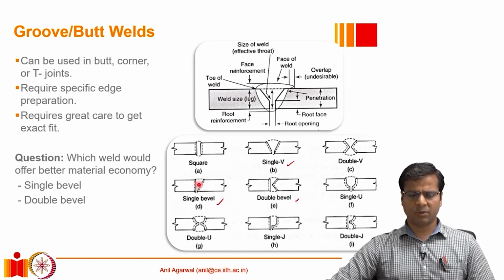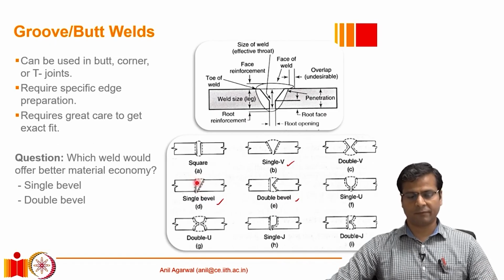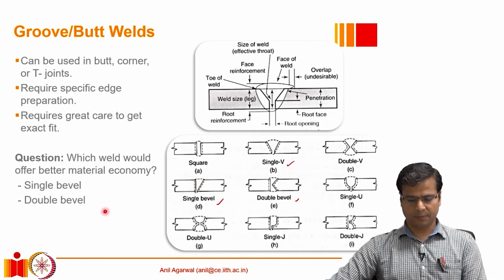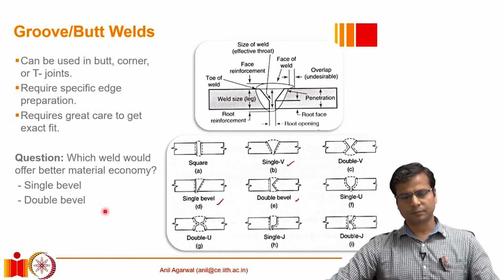So if that angle has to be maintained, and the depth is 18 millimeter, here we can calculate how much material has to be first removed in form of a groove and then filled back again with the filler material, right? And then we can calculate the area in a double bevel also for the same angle that has to be maintained. And you can very easily calculate that the amount of material that is required to be filled in case of a double bevel is much smaller than the amount of material that is required to be first removed and then filled in case of a single bevel. Okay, so double bevel is a more economical option from material point of view.